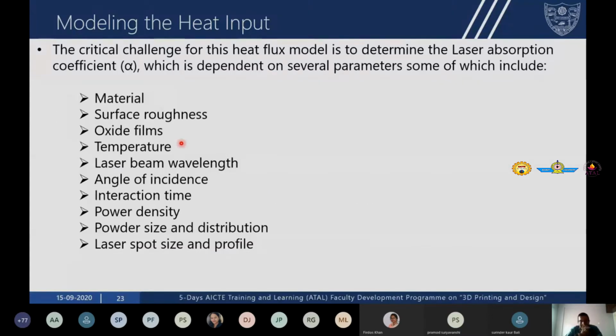One of the important challenges in the computational modeling of laser additive manufacturing is the laser absorption coefficient alpha. This absorption coefficient alpha depends upon several parameters, right from the material which you are processing. For example, if you're looking at two materials such as aluminum and titanium, aluminum being highly reflective will have a lower absorption coefficient when compared to that of titanium. The absorption coefficient alpha also depends upon the surface roughness of the material, whether any oxide films are present, what the temperature of the material is, and the wavelength of the laser.